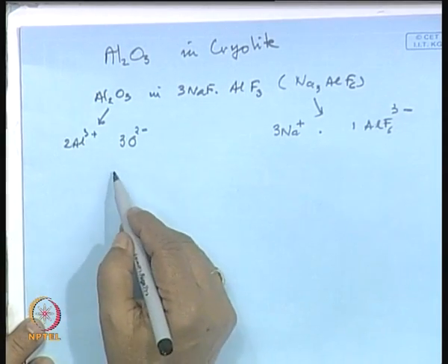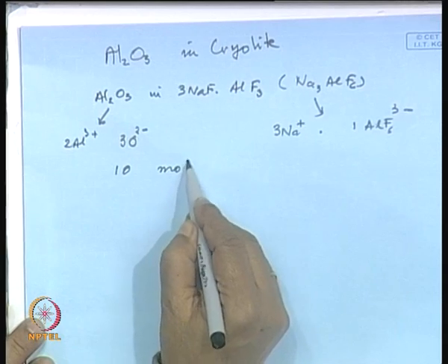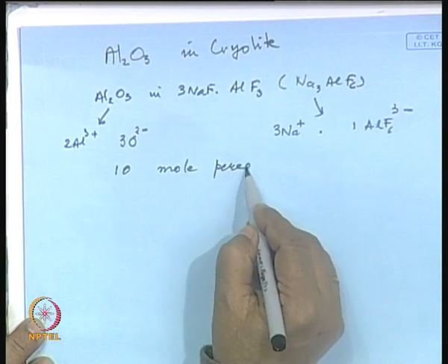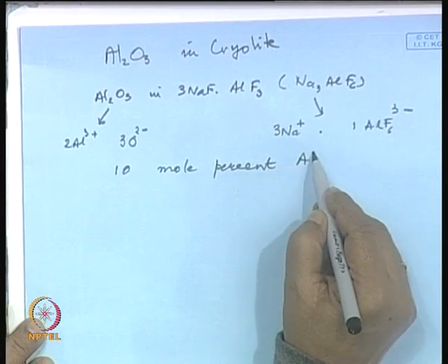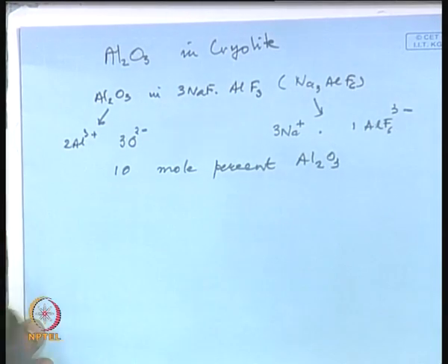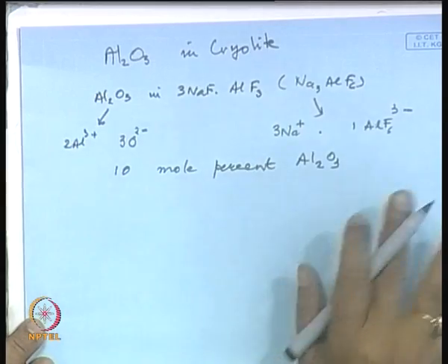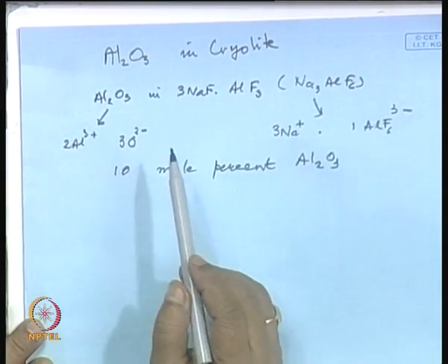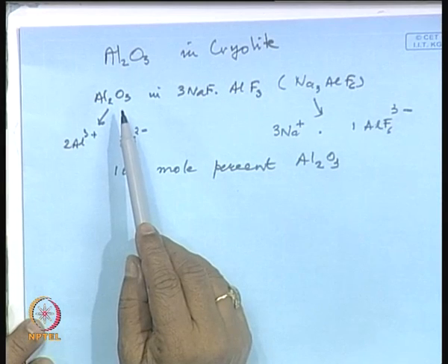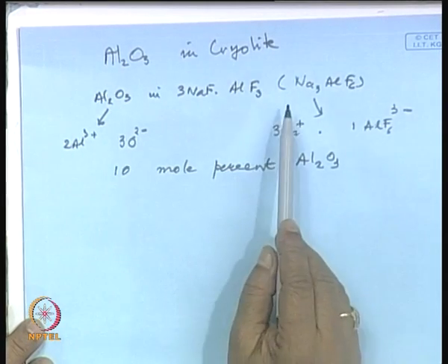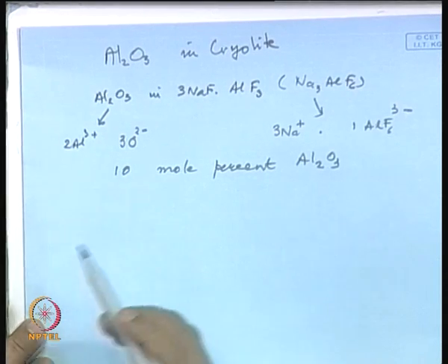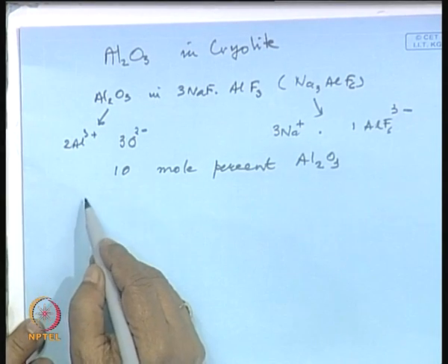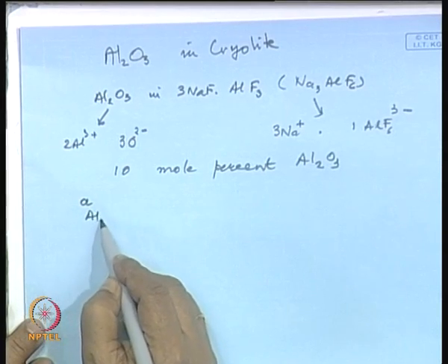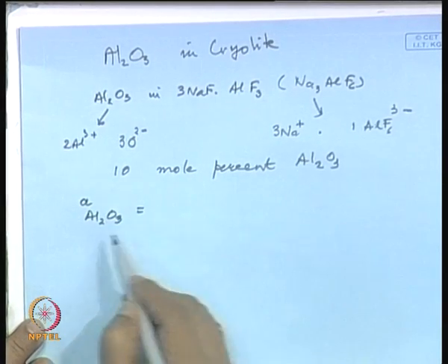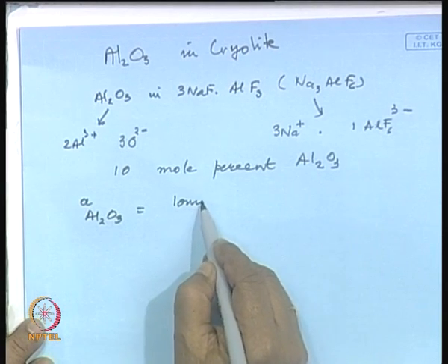Now, assume, to make it simple, that we have 10 mole percent Al2O3. The earlier calculation was for 15 mole percent, but let us say 10 mole percent, means for 1 molecule of Al2O3, you have 10 molecules of cryolite. Now, what is, according to Temkin's equation, the activity of Al2O3? It will be the ionic fraction